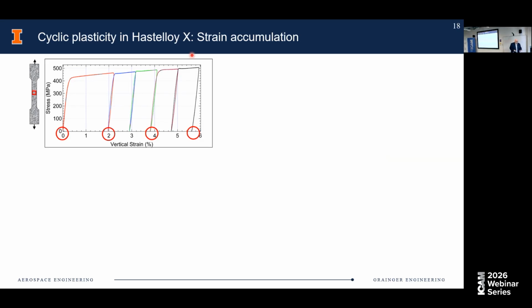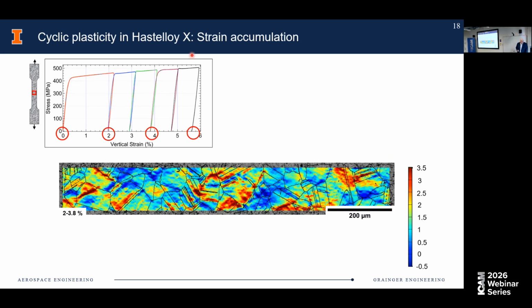And essentially, using this high resolution technique, we would correlate residual strains between certain points, the ones that are highlighted. So if we look at what this mesoscale strain field looks like between 2 and 4, roughly 4%, you would get this. This is just uniaxial tension. So this is the dominant strain component. You have all of them, of course.